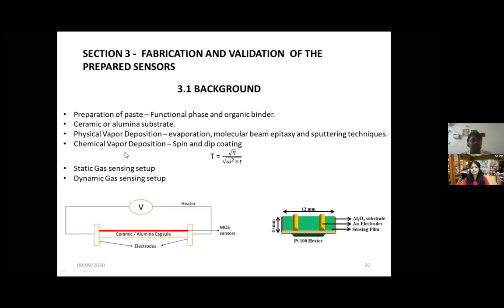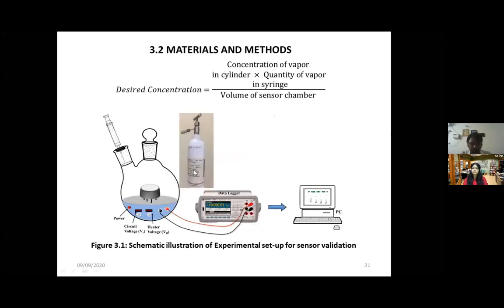And for validation, we have two setups, static and dynamic gas sensing setup. Dynamic gas sensing setup replicates the real world environment. But the problem we face in the dynamic gas sensing setup is, if there is an error, we have to go back from the first, and there is not much manual control. However, the static gas sensing setup is manually controlled. We have a pre-calibrated cylinder. Place the gas-tight syringe on the mouthpiece of this pre-calibrated cylinder, turn this. So based on the pressure, the gas goes back and is injected into the static gas sensing chamber.